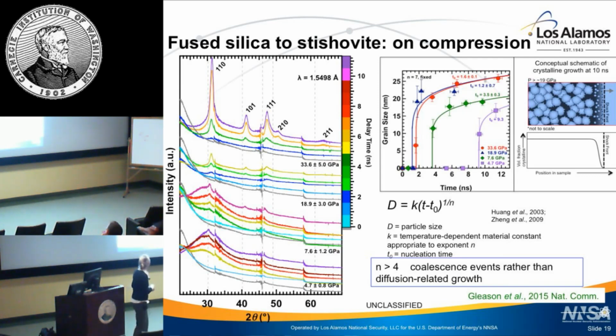So the n, this exponent here, is something like 7. Now, if it were a reconstructive phase transition, what is expected is that the time it takes to undergo this breaking and association of bonds is some long time scale. Moreover, it's likely diffusion mediated, right? And an exponent that would be associated with that is something like 3 to 4. But I cannot fit 3 or 4 or anything close to these data. I get something more like 7.